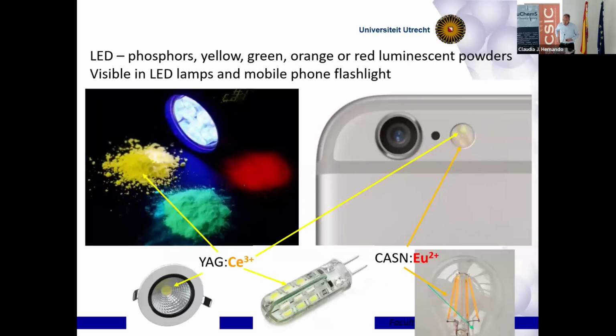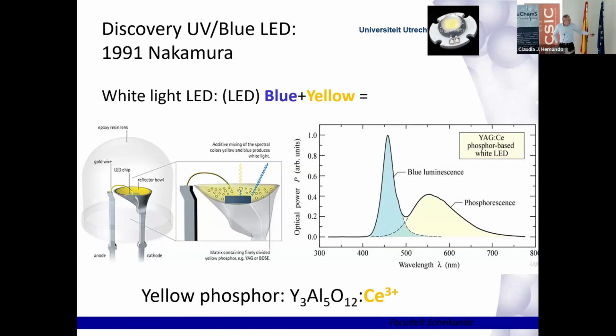And you can also see it if you look at your mobile phone. In the back, you may see the flashlight. You see a little yellowish dot. That is YAG:cerium. Now, to make warmer white light, you can see here that the spectrum lacks red. Red is beyond 600 nanometers. This is really a cool white LED, not very pleasant.